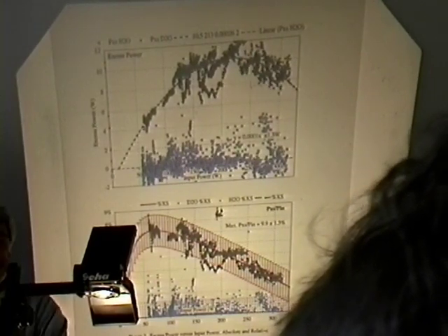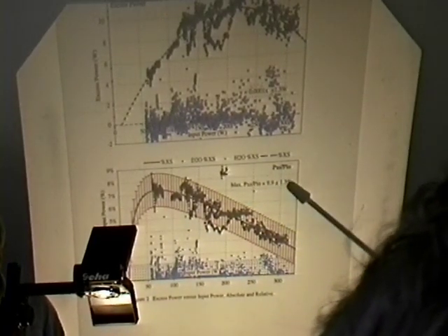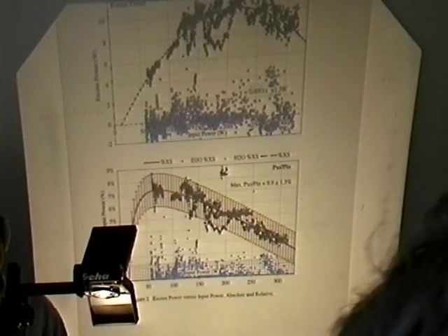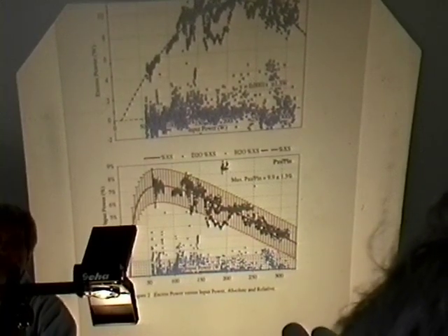But we have something like 10 watts of excess power, and if you look at this in terms of a percentage, with some assigned uncertainties, the largest excess power that we observed in this experiment was called 10%, plus or minus 1.3%. But the signature is only in the range of sort of 7-8%. A signature sufficiently large for us to be confident that it's a real effect, but you're also doing a lot of work. You're putting 300 watts of input power in to only get 10 watts or so out.